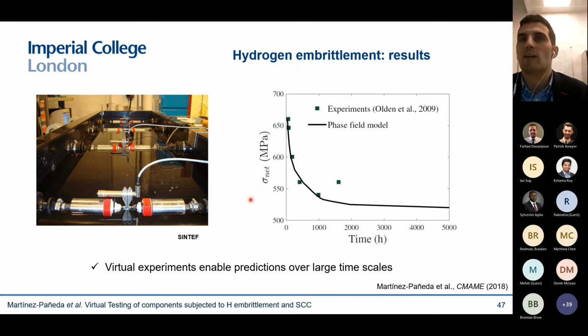What they were hoping is that some of these would be loaded at a remote stress small enough that no matter how long they waited, the sample would survive. As a result, they could deliver the threshold stress level below which you can load your structure safely. However, as you can see here, the symbols are the experiments. All of them fail relatively early.